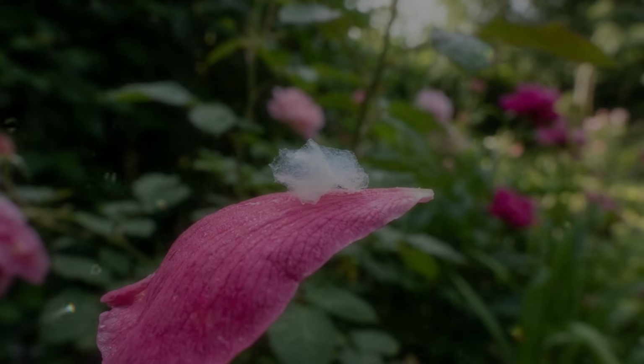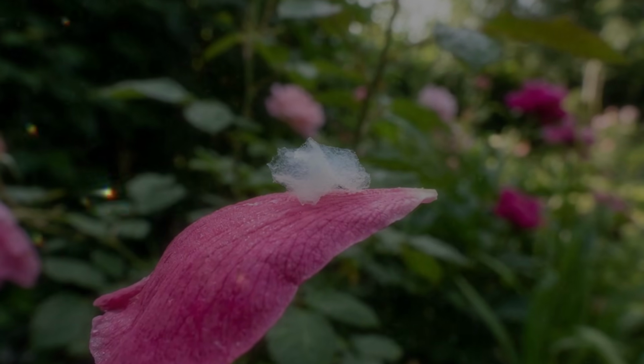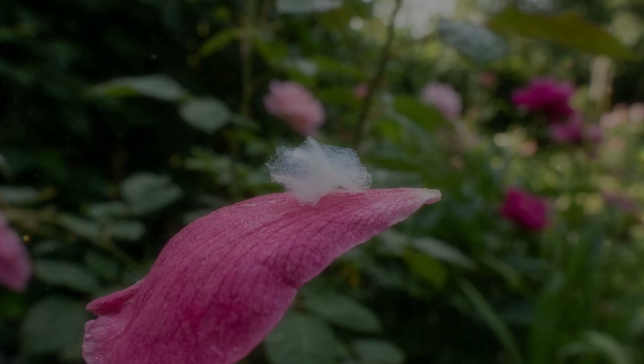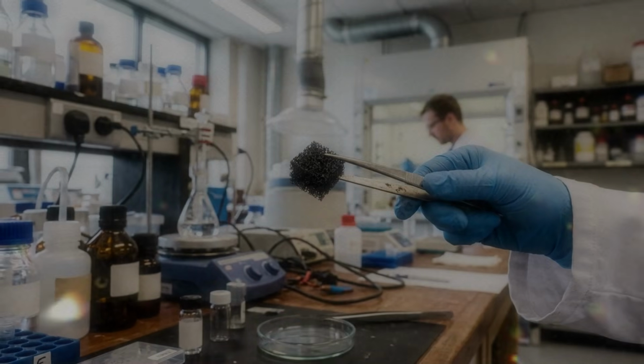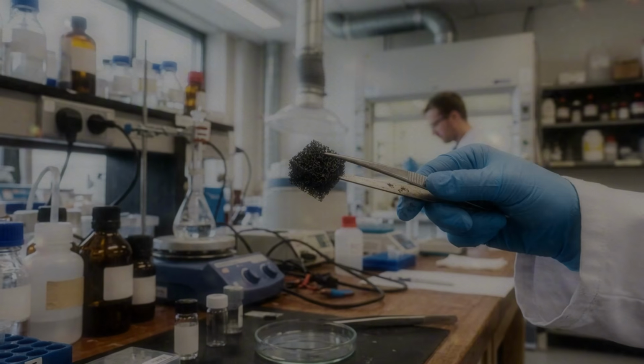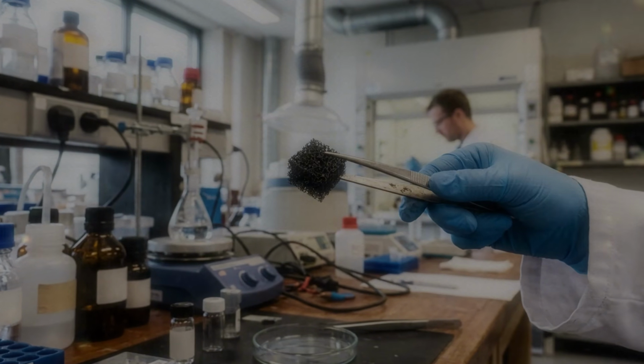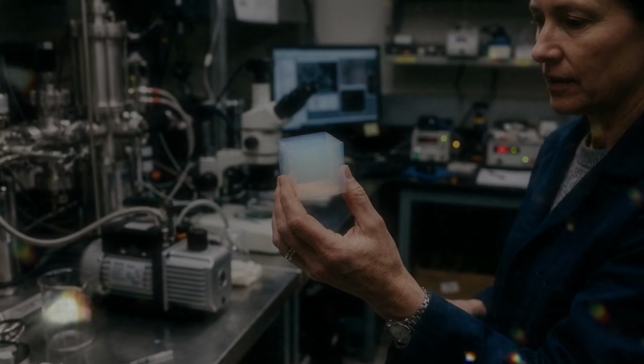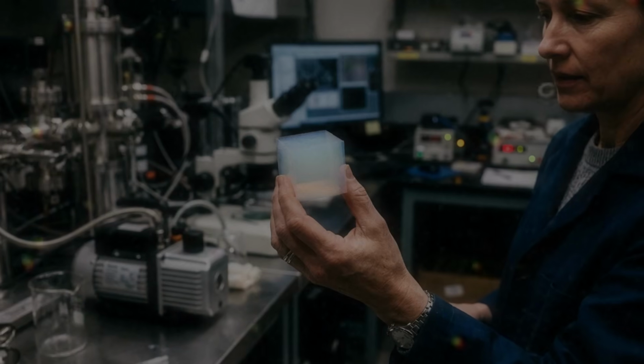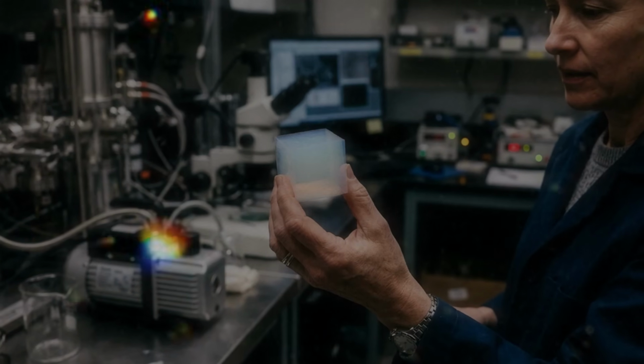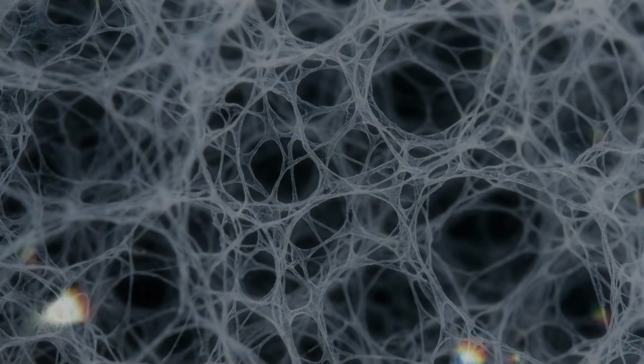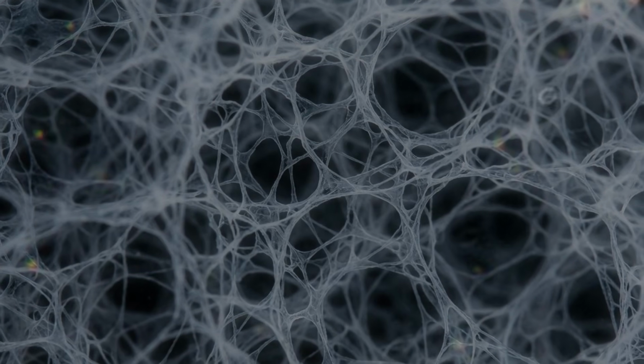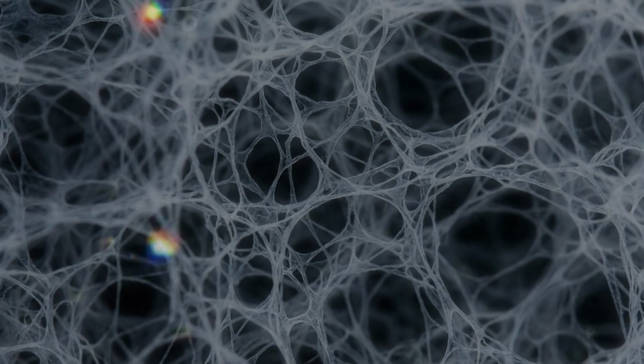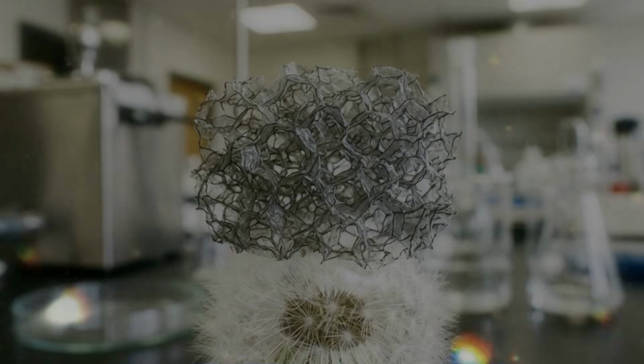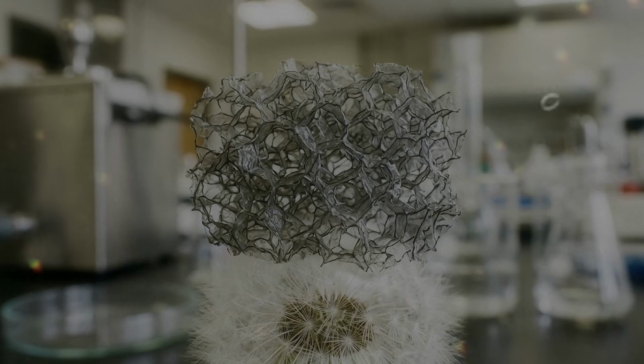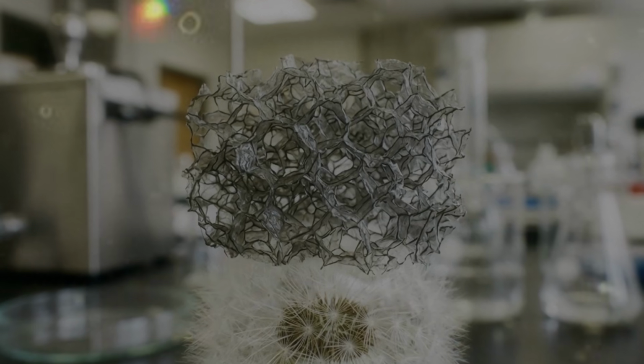At this point, it may still contain a large amount of oxygen and other chemical groups. Additional heating can remove some of them, restore more of the carbon network, improve electrical conductivity, and strengthen contacts between sheets. Heating must be done in an atmosphere that prevents the carbon from simply burning. The sample may be placed in an inert gas or under reduced pressure. Temperature is increased according to a planned schedule. Too little treatment may leave poor conductivity. Too much may damage the structure, remove useful surface groups, or make production unnecessarily expensive.